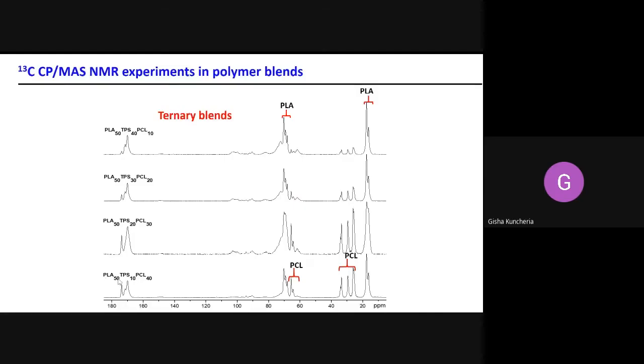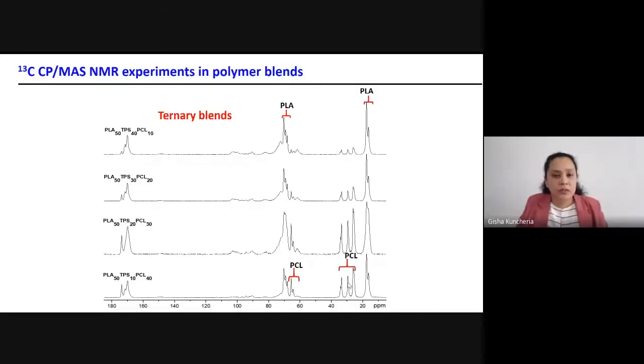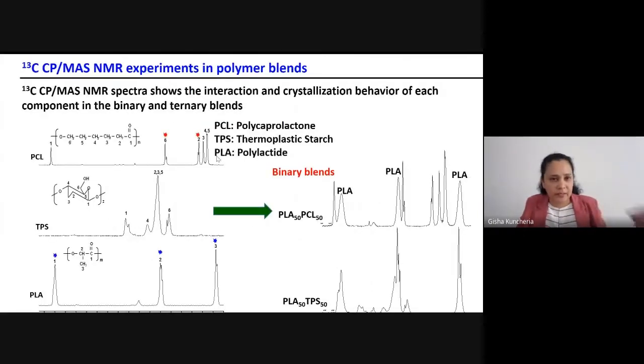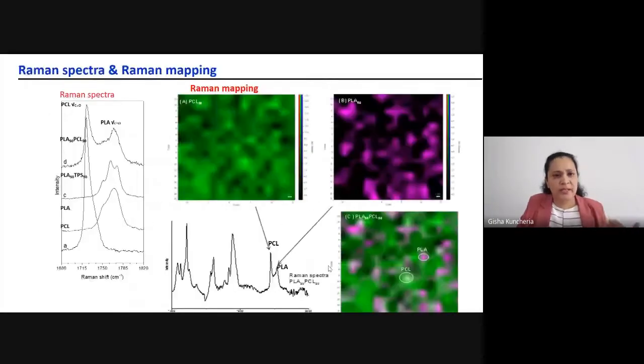Amount of PCL, PLA retained its crystallinity. So these points, crystallinity or interaction, all this we can determine from this NMR spectroscopy. And I tried to find out what is the reason for these changes in the binary blend. For that, we went for the Raman spectra and the Raman mapping.